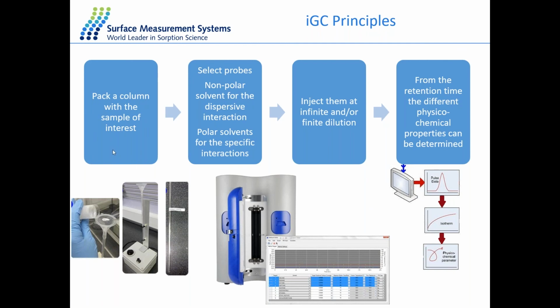So what you would first do during an experiment is pack the column with the sample of interest. You can then go ahead and go to the software. And what the software does, it allows you to choose some polar probes and some non-polar probes. The non-polar probes kind of give rise to more dispersive interactions, and the polar probes, specific interactions. You can then choose how to inject them. So we can inject them at very small concentrations, infinite dilution, or larger concentrations. And then you can start your experiment. Upon the interaction between these probe molecules and your sample, you would obtain different retention times, which you can go ahead and analyze the peaks.